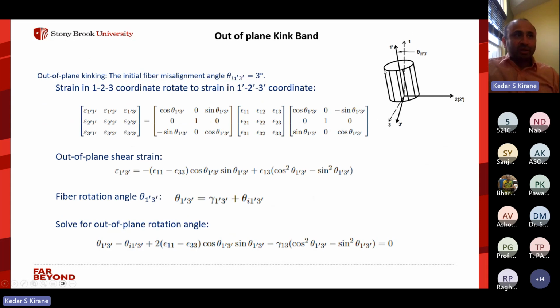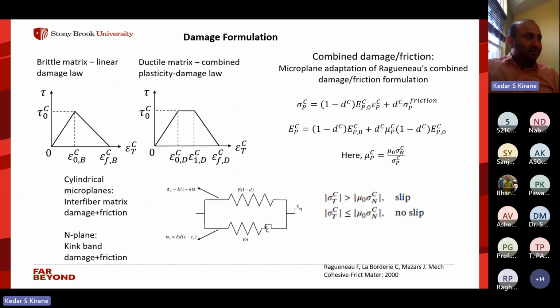There is also the out-of-plane possibility. So we can do the same for the out-of-plane also. So this is a key feature here: calculating local shear and then adding it to the initial misalignment angle to keep increasing the local rotation of the fiber. And then we have damage laws on the cylindrical microplanes and the transverse planes.